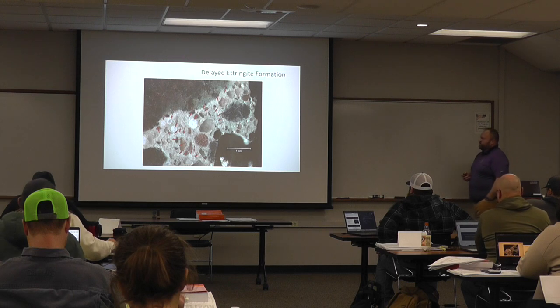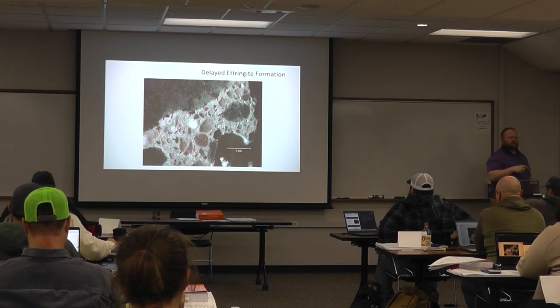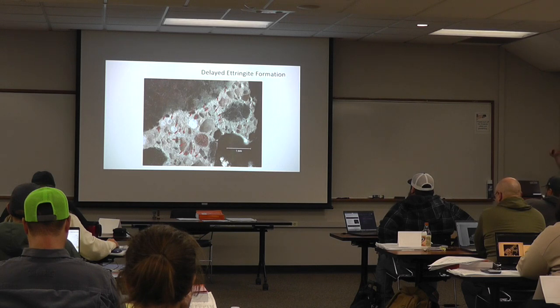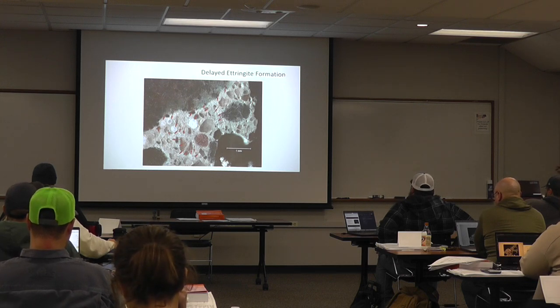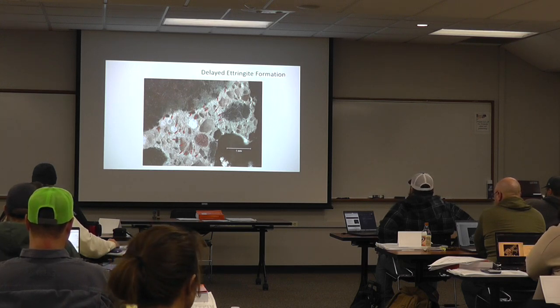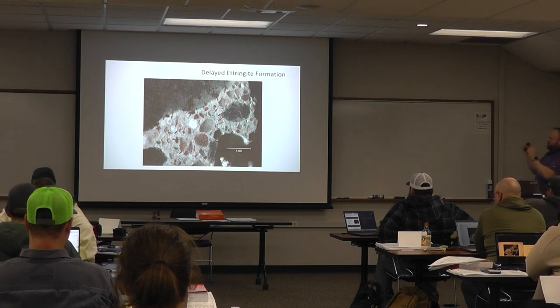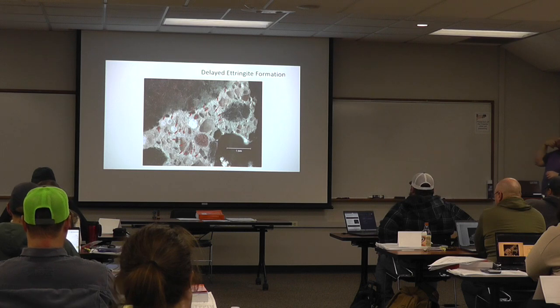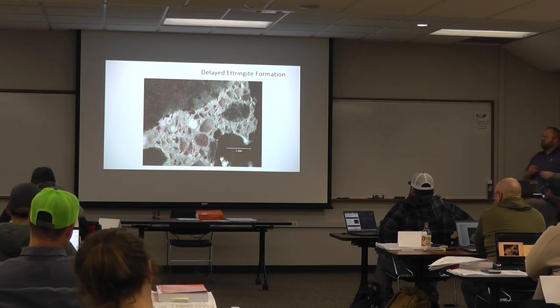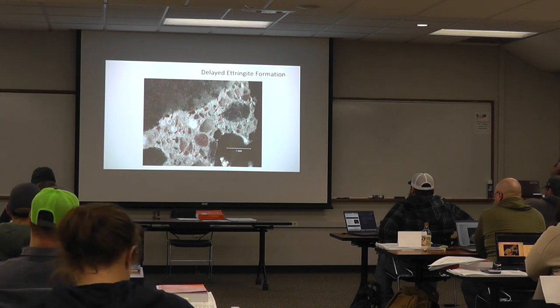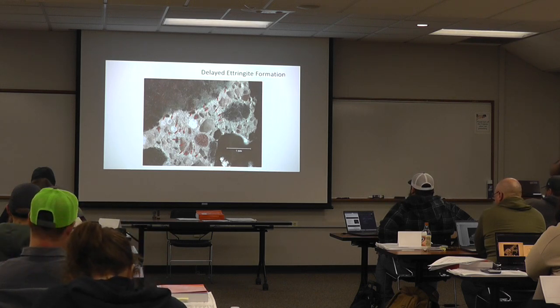When it comes to delayed ettringite formation, at about 160 degrees when the hydration reaction is happening, well, let's back up a second. Ettringite is a normal byproduct of the hydration reaction. It's one of the minerals that forms during the hydration reaction. At about 160 degrees, it stops forming. Everything else keeps hydrating, keeps going, filling up all the spaces. But then, once that concrete cools down and is in service, the ettringite will start forming again. When it starts forming, it tries to find areas to form into. It starts pushing everything out, making some space for itself, and that's when you can start getting cracking.